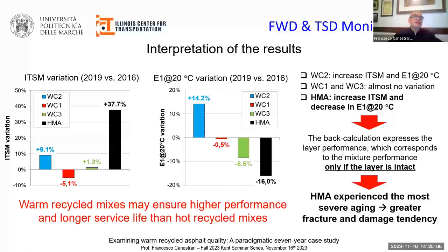Therefore, it can be deduced that HMA likely suffered the most severe aging in the field, which made the pavement more prone to fracture and damage, because we observed at the same time an increase in the indirect tensile stiffness modulus over time. And this increase in the stiffness can be attributable to the in-service aging of the asphalt mixture. Overall, the results obtained indicate that the warm recycled mixtures can ensure higher performance and longer service life than hot recycled mixtures.